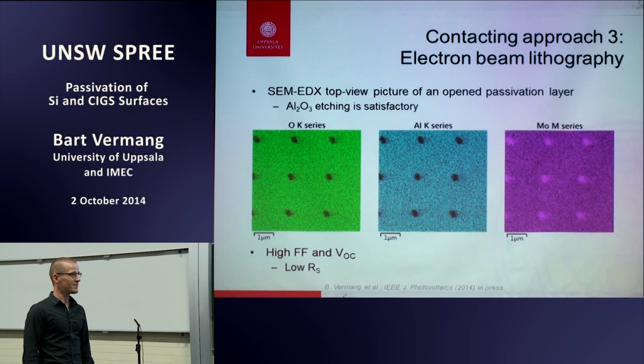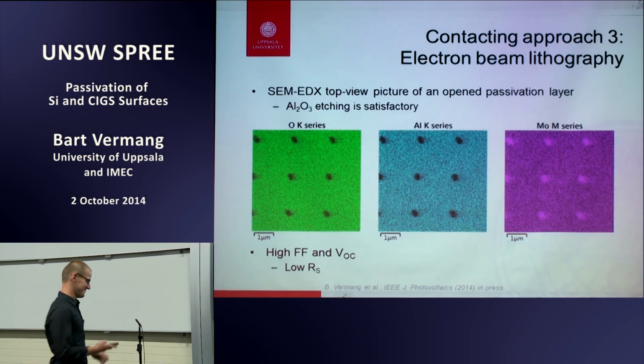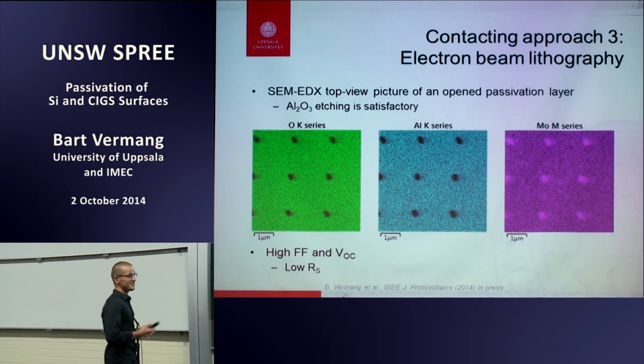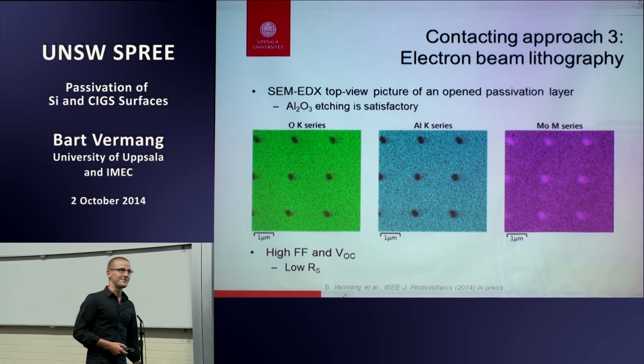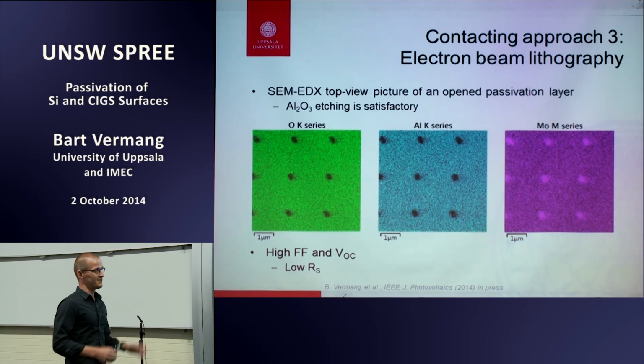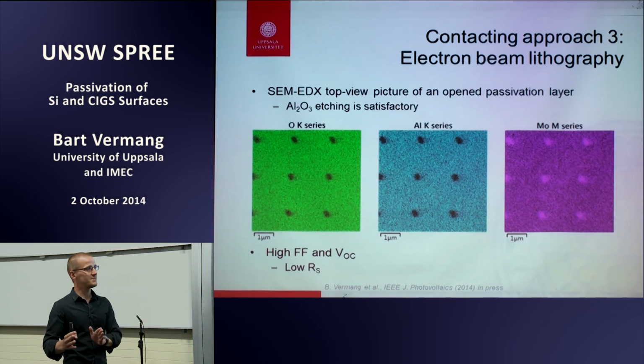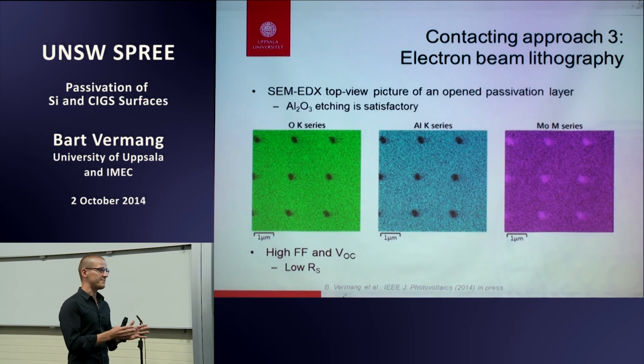So, what sort of coverage areas did the three approaches have? Thanks for the question. Good question again. So that's what we did. We scaled it from the silicon part to the CIGS part, taking into account diffusion lengths and all these kinds of things. So we have the same area. It's somewhere between 2 and 5%. That's what we're aiming for all the time. So 2 to 5% of the rear surface is contacting area. And all the rest is passivated area. Or should be passivated area.